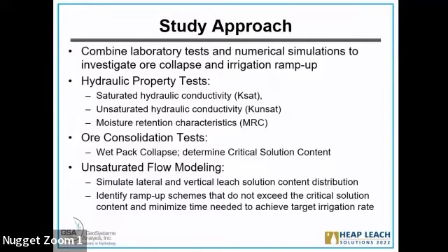Because collapse under wet conditions is no stranger in soil science. Like loess material in the China area, when they face water wetting, the major collapse starts occurring. There's many years of research done in this area, but still no easy or conclusive model can be concluded for this type of behavior. So it's a very complex process, but we intend to use a so-called critical solution content, which means when we meet a certain water content, the ore major collapse will start, and we will try to avoid that from happening.